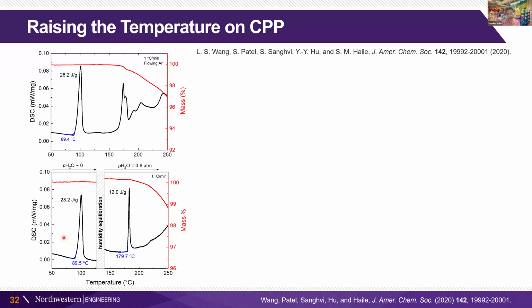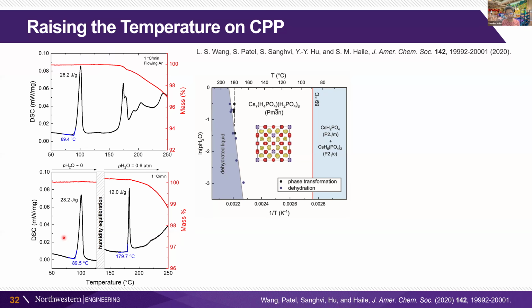This was quite surprising to us. And we put this all together and noticed that there's a very small sliver of a new phase that you can see at that high steam partial pressure. That's what that second transition is when we first go through